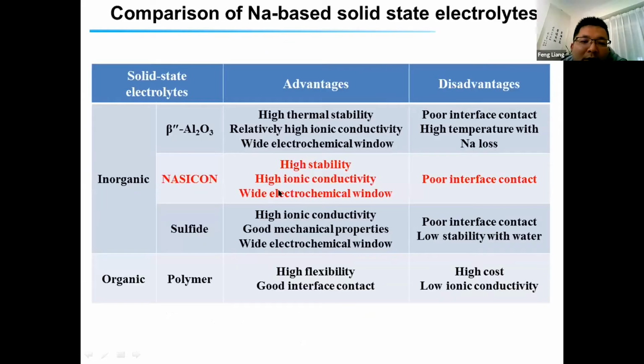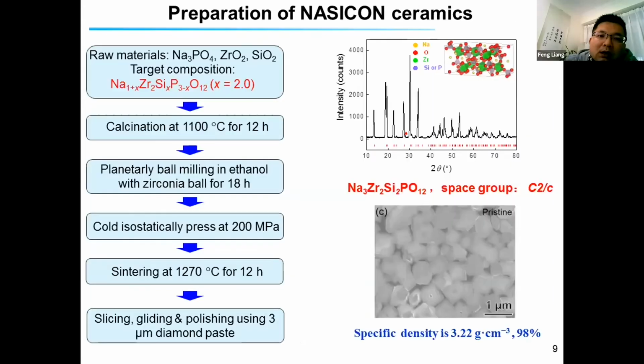Therefore, we use the NASICON structure solid electrolyte as the separator for the hybrid sodium battery. It has a high stability, high ionic conductivity, also the wide electrochemical window. But of course, the problem is the interface contact because it's a solid, inorganic solid. Okay, so this is the preparation of this NASICON ceramics.